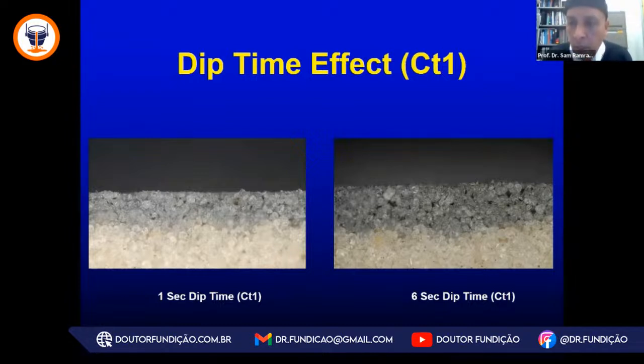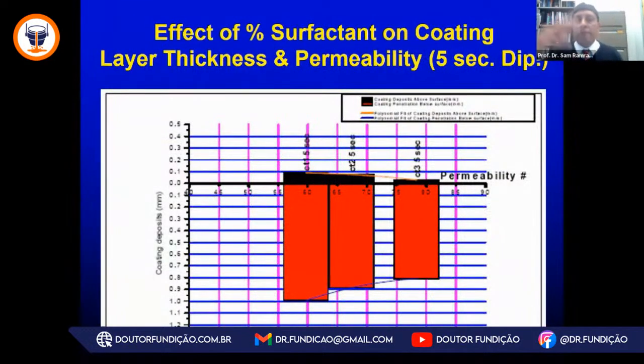But how much? How much proud coating? Coating is not for free. And then how much penetration? That's a function of dip time. Because if that wet layer goes deeper into the sand binder system, it could potentially weaken that sand binder system in the casting experience. And we have measured the permeability as a function of the coating thickness.